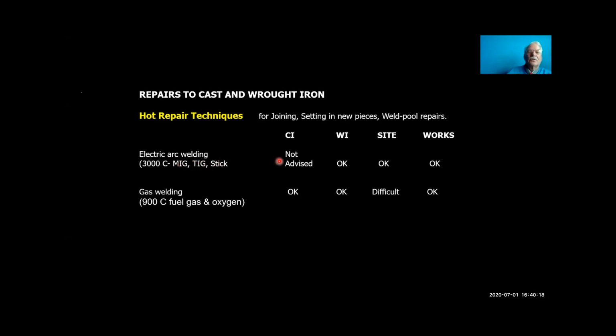But this is not great news for castings, because being brittle, castings will be shocked and usually the weld will fail. You can weld cast iron, but it's not recommended. It's okay on wrought iron. It's all right on a site, except that, of course, historic sites don't like, we don't like the risk of hot work on historic sites.